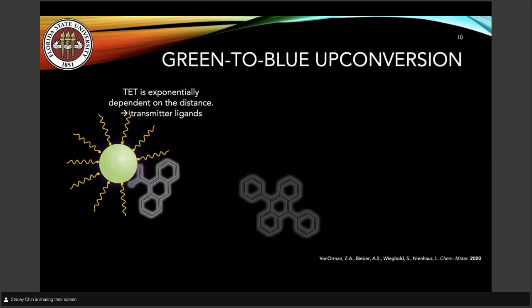Okay, so I'm going to start out with green to blue upconversion. In particular, we're doing this with cadmium selenide nanomaterials. One of the big issues with these little nanomaterials is that they have these long spaghetti-like ligands on them. And these hinder efficient transfer of the exciton, due to the fact that this triplet exciton transfer, TET, is exponentially dependent on the distance between your donor and your acceptor.